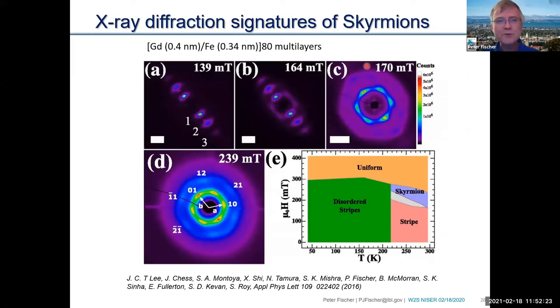Now, what we did is we used a gadolinium iron multilayer system, again, pretty well known, but an interesting system to study. And it was well known from this study here that when you change the magnetic field being applied at a certain temperature, the gadolinium iron goes from a stripe phase, which is characteristic in the diffraction, where you see these linear kind of peaks, and it actually transforms, by slightly increasing the magnetic field, into this hexagonal pattern. And the hexagonal pattern is then the characteristic of a skyrmion lattice. So we were able to see, around this field transition at about room temperature, a transition from a stripe to a skyrmion lattice phase.